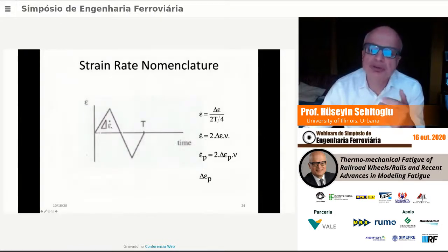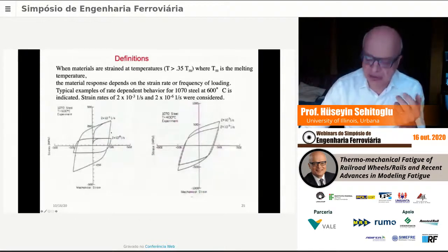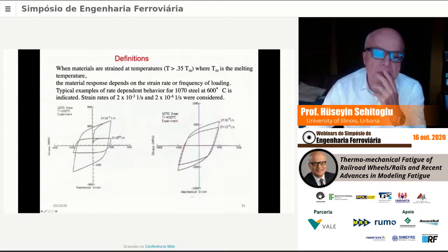So it's important to know what the rate is in these experiments, because the material at high temperature is rate dependent. And that's what's being explored here. If we look at our wheel steel, 1070 steel, 600 Celsius, that's 2 × 10⁻⁶ 1/s. This is 2 × 10⁻³ 1/s. So you could see a huge effect of strain rate on the mechanical behavior. So it's important to have a stress-strain model, a constitutive model that accounts for this rate effect.